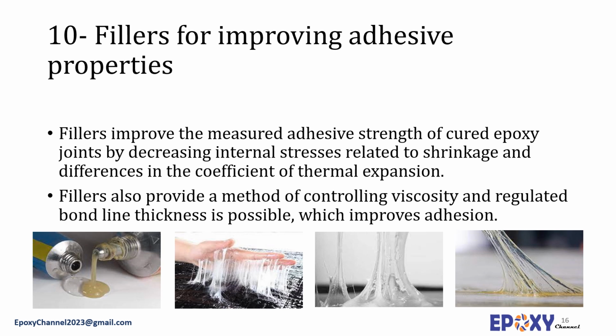Fillers also provide a method of controlling viscosity so that a predictable and regulated bond line thickness is possible, which improves adhesion. The degree of tensile strength improvement is often in the range of 50 to 100%. Although the addition of fillers results in an improvement in the tensile shear strength, it also often results in a decrease in peel or impact strength. This is due to the reduction in elongation and toughness that is often accompanied by the high filler loadings in